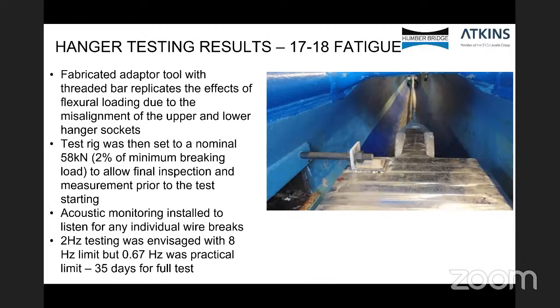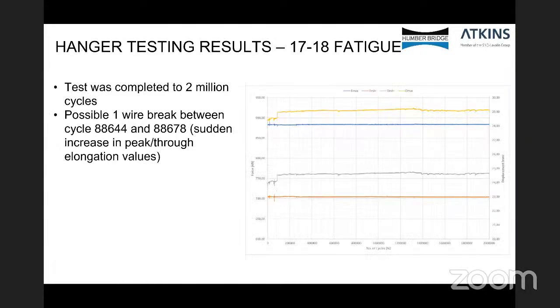Acoustic monitoring was installed to listen for wire breaks throughout the fatigue testing. Now, the fatigue testing was carried out at 0.67 hertz, and that took 35 days for each hanger. So the two hangers were in the machine for over 70 days as the fatigue cycles were being loaded. If you look to the next slide, please.